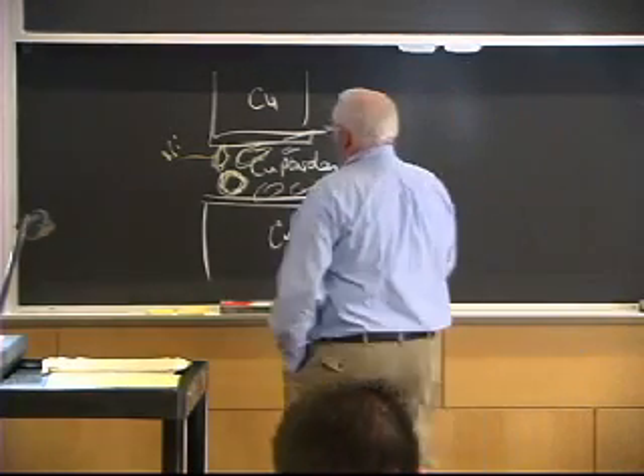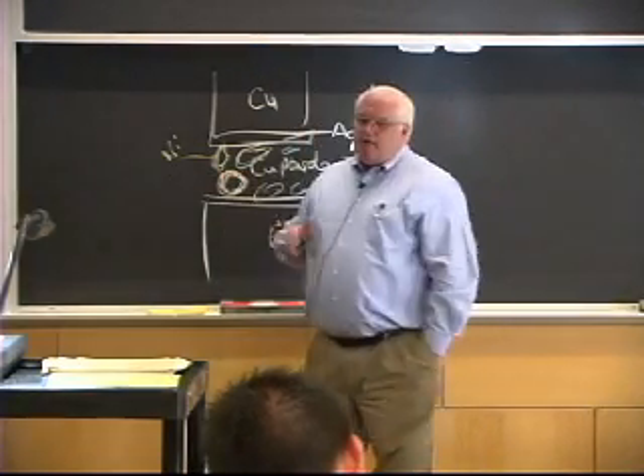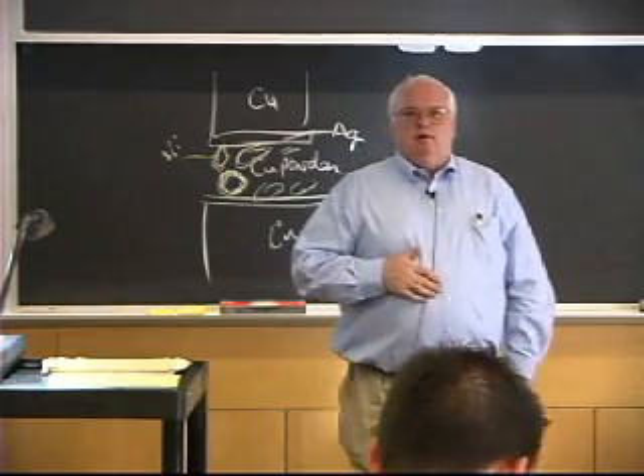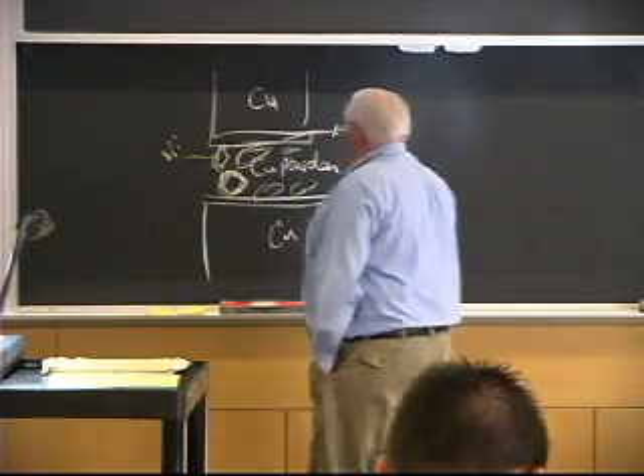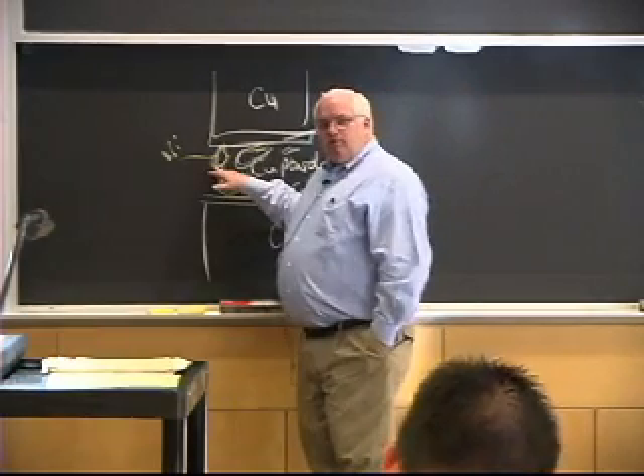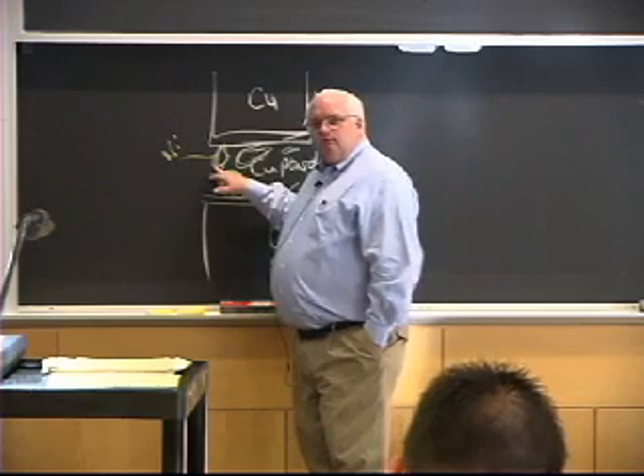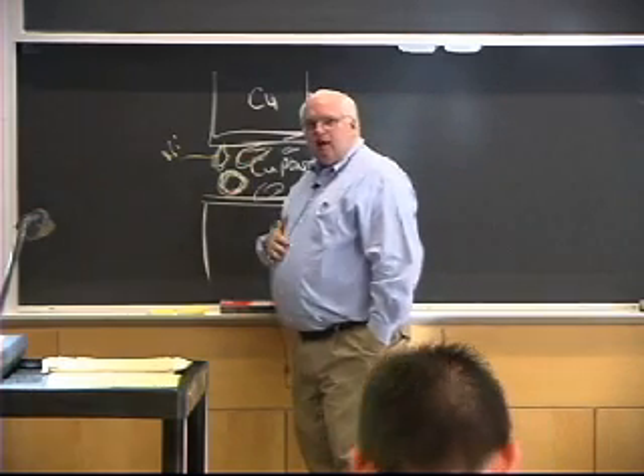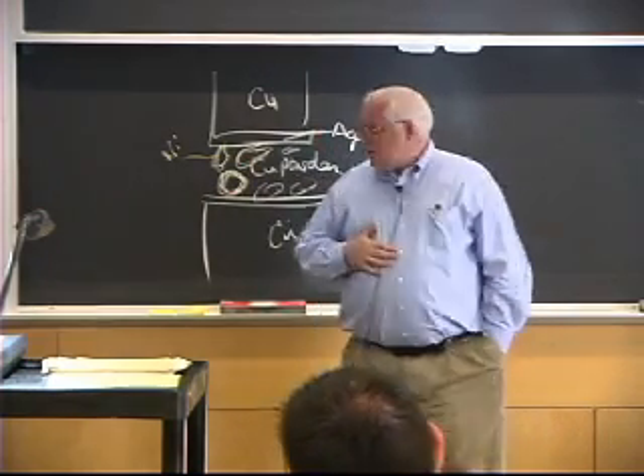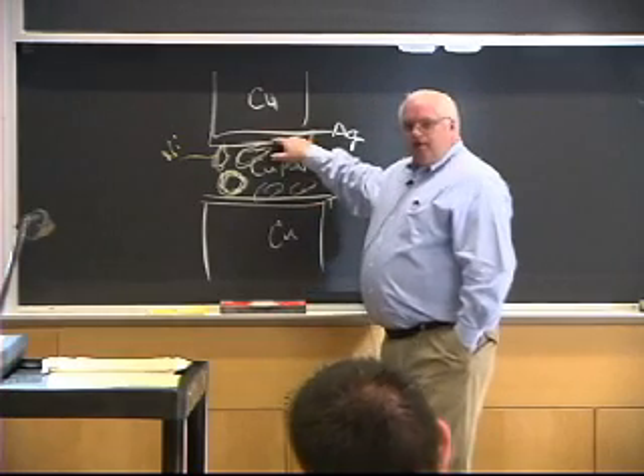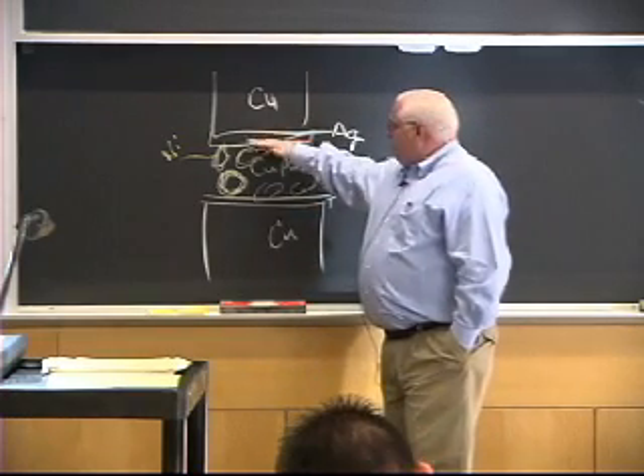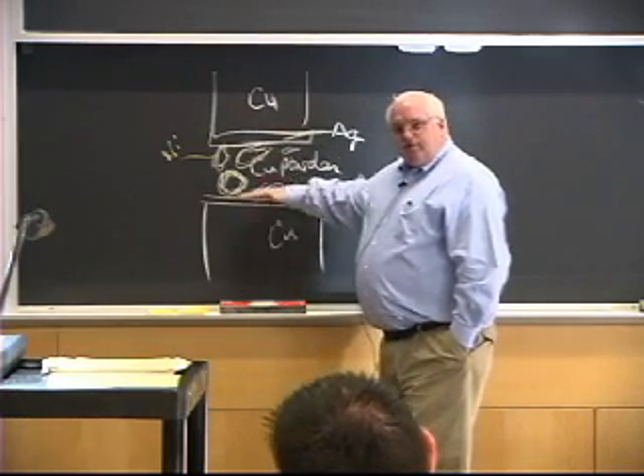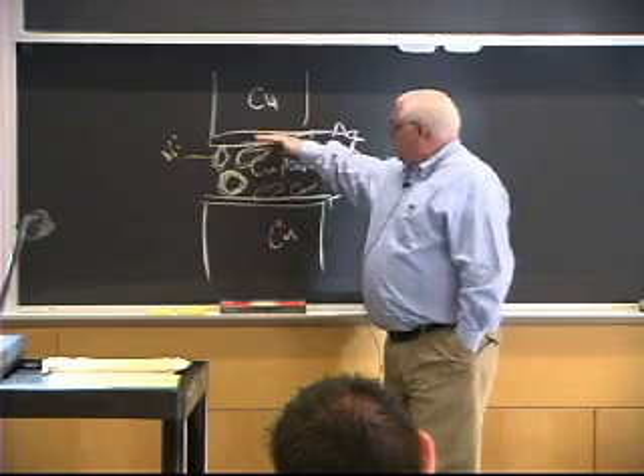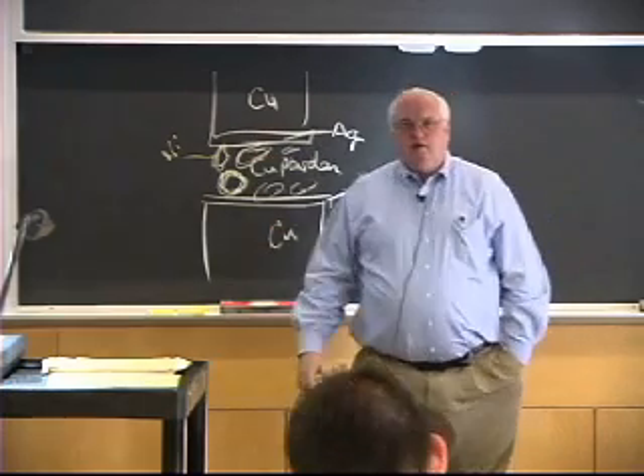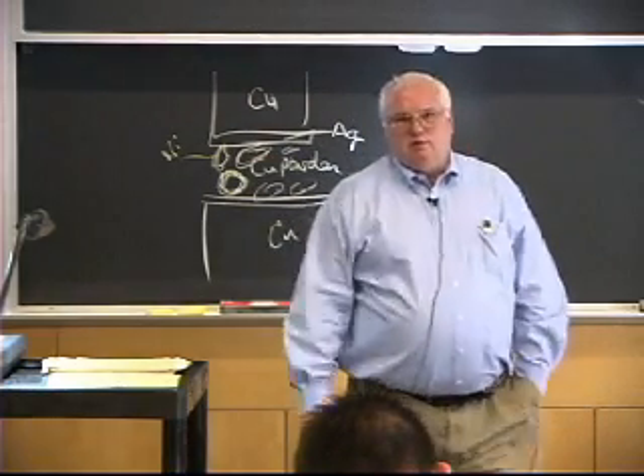The nickel layer here is probably only 5 to 10 microns. So the powder is probably 40 to 60 microns, and you've got a 5 micron coating on it. So it's 10% of the diameter of the powder, approximately. And this silver might be 50 microns, and you're going to infiltrate. Actually, the silver depends on how thick a layer you want to infiltrate. You can make it 20 thousandths or 30 thousandths, so far as that goes.